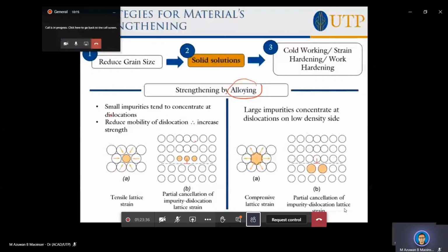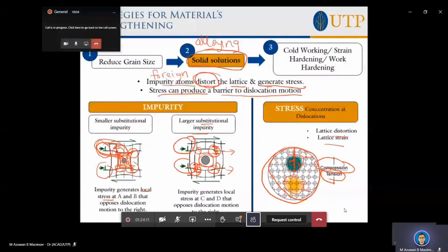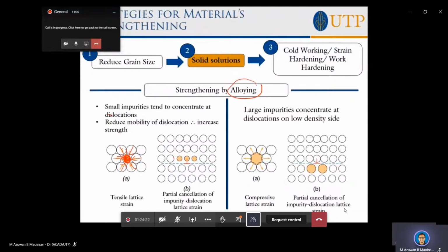This is what I mentioned just now about alloying. This is just to demonstrate what happens if you have a smaller solute atom inside the host. So all these are the hosts. Now this is small. Because it's small, the surrounding atoms tend to pull in. That means they will be under strain, pressing onto the impurity, the foreign atom or the solute. Because it's small, it's going to relieve some stress on top of that edge dislocation. Remember here you have compression and below is tension. Your alloying element, your solute atom, because it's small, is going to partially cancel the compression stress experienced on top here.